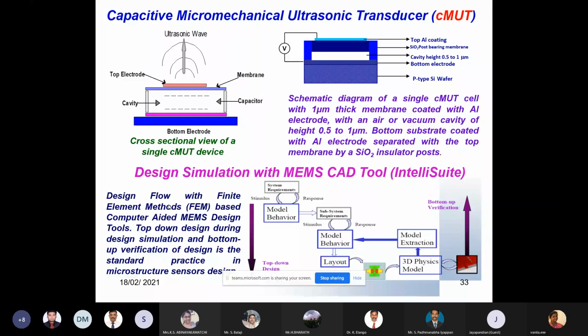Then it can hit the target material, like a reactor vessel. If there is a micro crack, the reflected beam will have a path difference compared to the beam reflected from other surfaces, because in a micro crack it enters and comes out. Then, when it reaches the same membrane again, we remove the AC and DC potential, just to measure the capacitance, because the reflected beam falling on the membrane causes deflection again. The air cavity capacitance varies, and that variation shows the reflected beam. That way, one can have ultrasonic non-destructive evaluation of material, for any crack or micro crack formation.